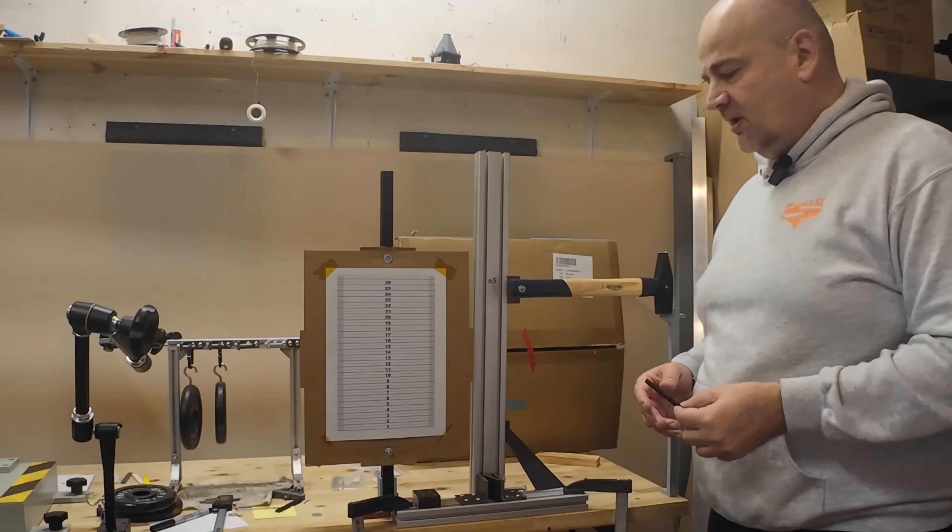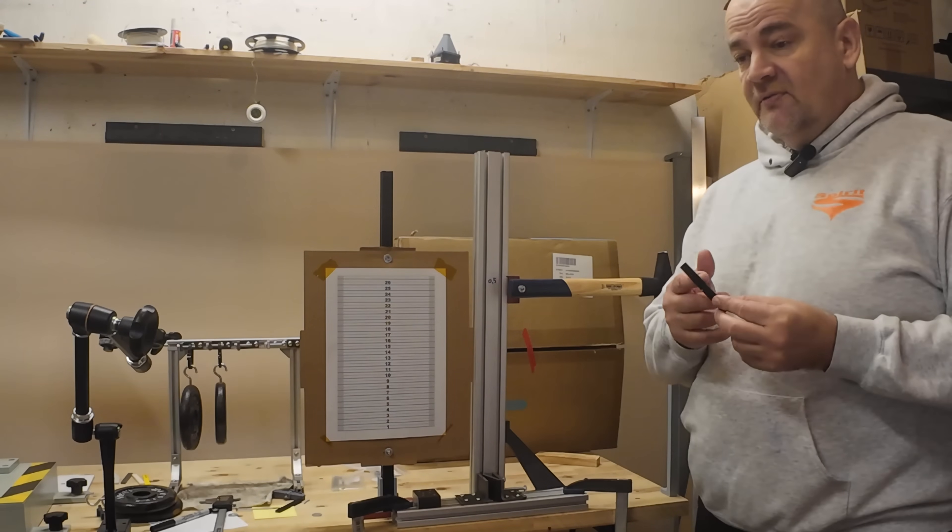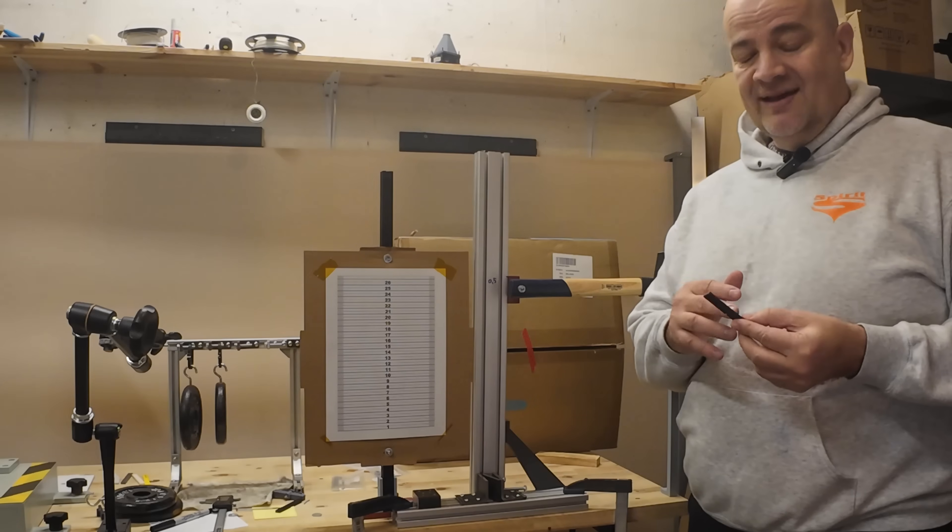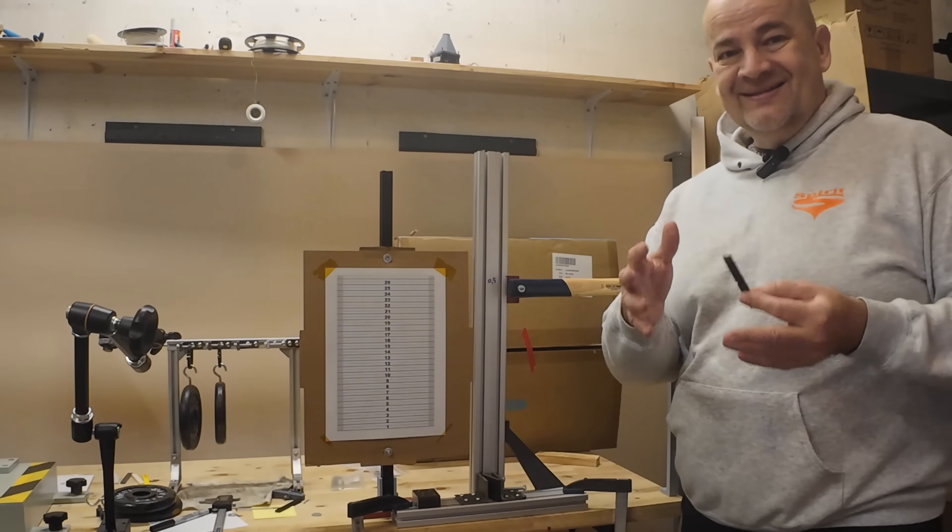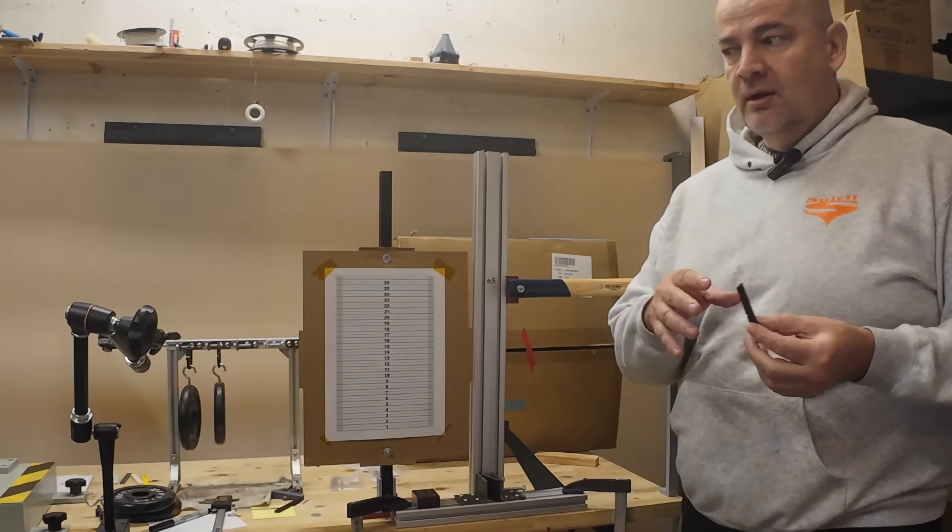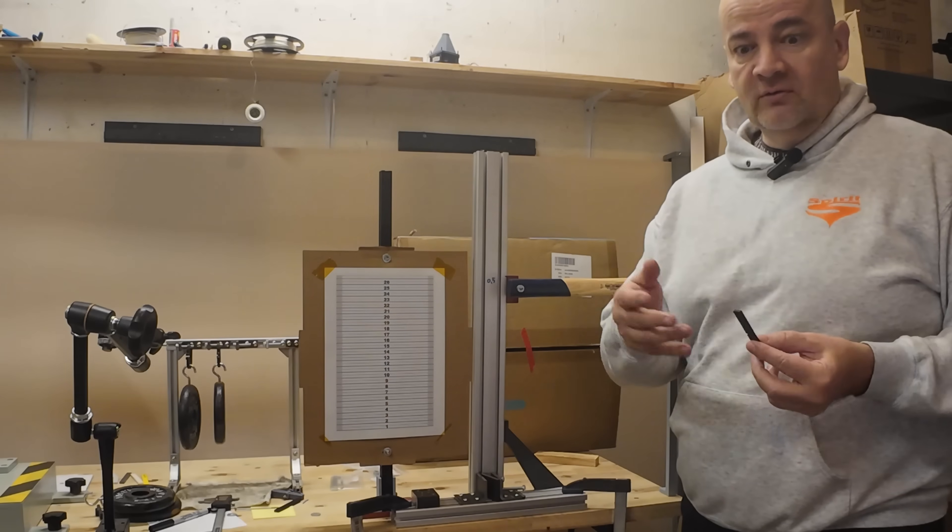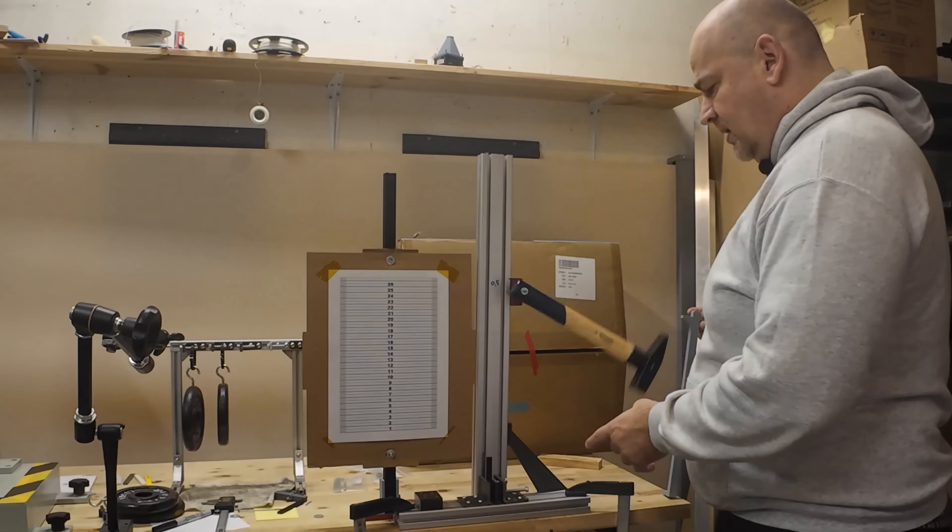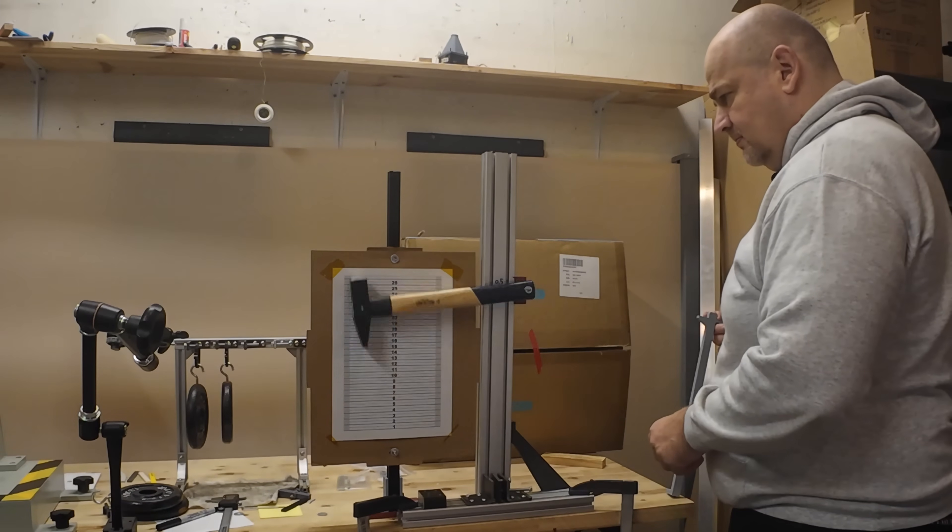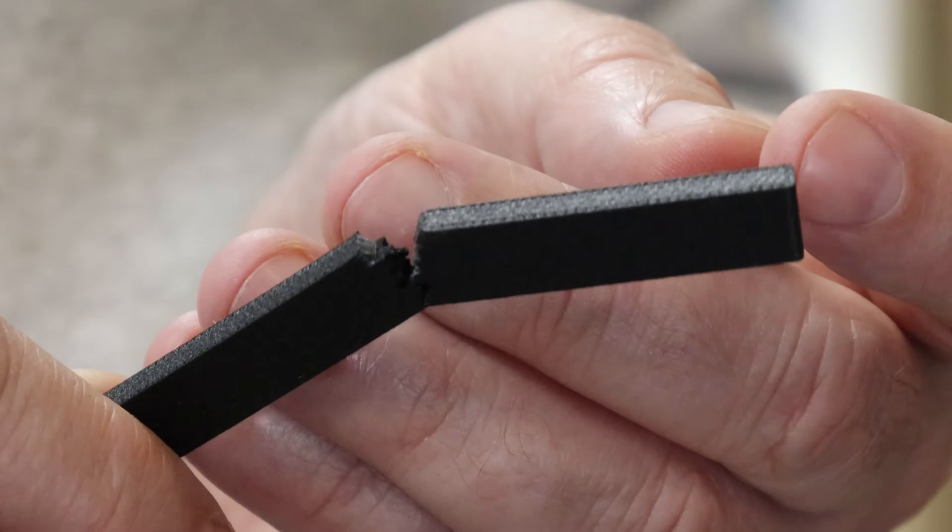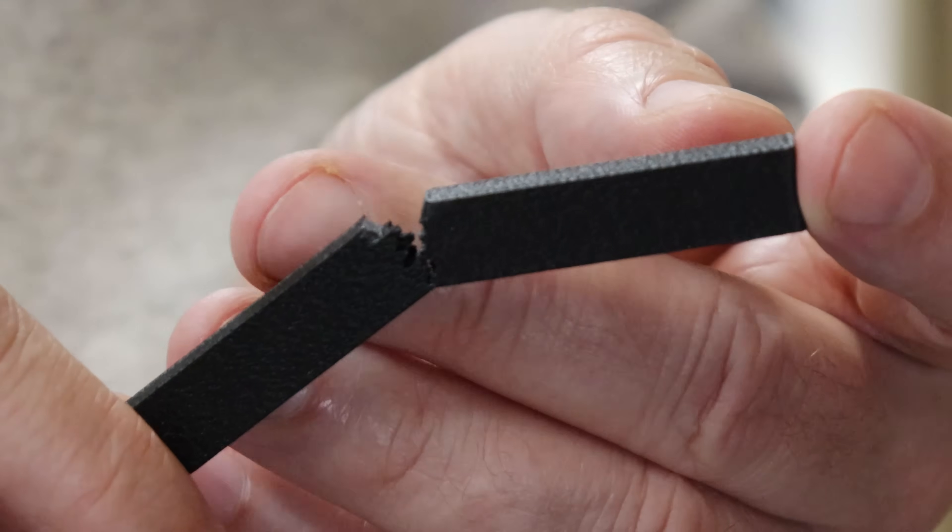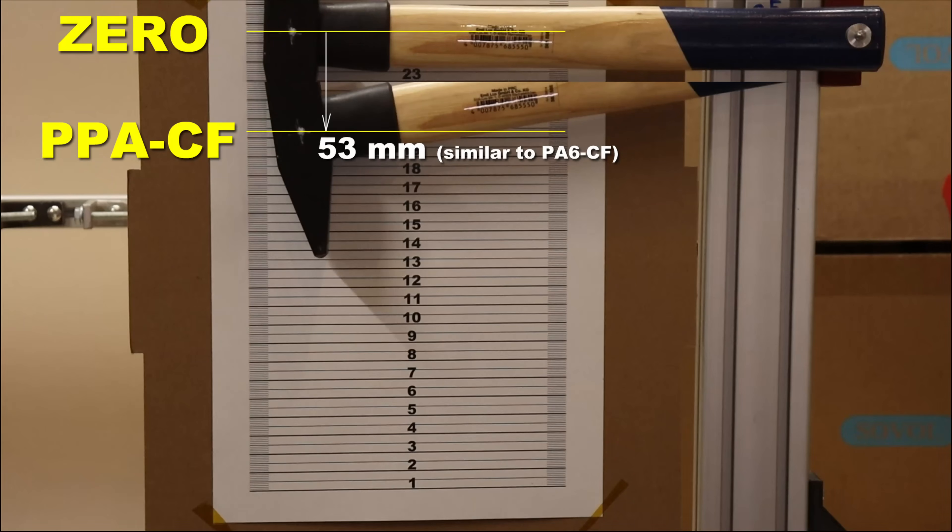The impact test with this 1.5 kg hammer and the filament itself is very brittle. We will see if that is the case with the 3D printed objects too. The PA6 nylon filaments were quite brittle, which is unusual for the nylons. Well, we will see how the PPA performs here. PPA, zero position. At the first look it is tougher material compared to the PA6, but let's analyze the footage. Only now I can see that it is very similar to PA6-CF, which is tougher material compared to the PLA or PETG, but more brittle compared to the average nylon I tested so far.